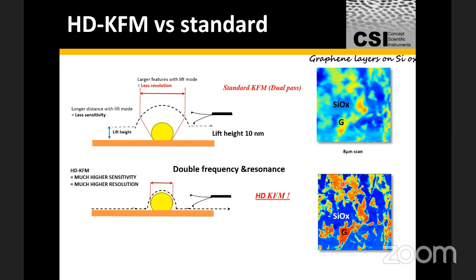So you can see that within a flake on the silicon oxide itself, we're now able to go inside and really look at it. So if you're going to deposit some, for sensor applications, for example, you're going to functionalize the graphene layer itself. You can now today expect to be able to get characterization within that small flake itself, and hence understand whether the functionality that you're imparting has actually translated or not in a certain sense, and that's really what I want to highlight.